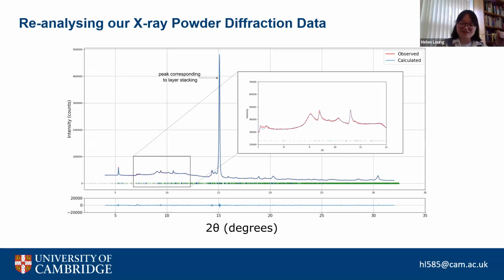And then we randomly introduced a deviation from that stacking pattern in the form of another known stacking vector. So for example, A or B or C or D. And we essentially randomly dispersed these stacking faults in the stacking sequence of our supercell approach. But what I want to be clear about is we have very rigid translations that were allowed. So the translations between layers that were allowed were only A, B, C, or D. And so we essentially created a stacking fault model.